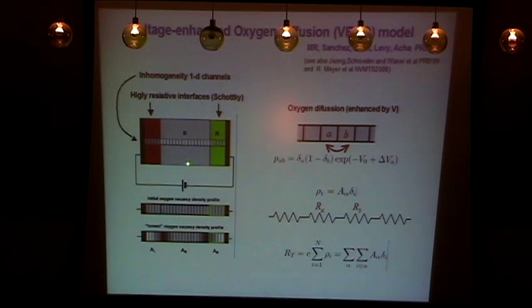So say in the bulk, for simplicity, we just consider A to be 1, and then at the interfaces, since they are Schottky interfaces, the resistance there is enhanced, mostly not because the system is different, since structurally it's the same system, but because the band bending produced by the proximity with the metallic electrode produces a change in the band structure, and that depletes carriers or whatever. In any case, you have a large resistivity there.